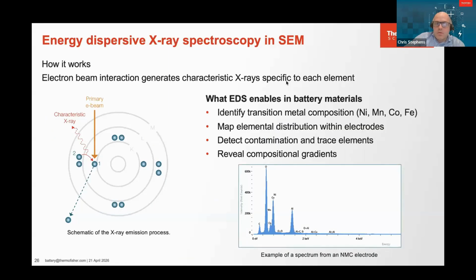So EDS, I'm going to start with, is energy dispersive X-ray spectroscopy. What we're doing is analyzing the characteristic X-rays which are generated when the electron beam itself interacts with the sample. This enables the user to qualify which elements are present and then quantify how much of each of those elements. The figure on the left shows how this works. The characteristic X-ray is what we're interested in, and this occurs when a core electron is ejected, a higher energy electron will fill the void, and then this will emit this X-ray. Because each element essentially has its own unique set of X-ray line positions, we can use this to determine what is present.